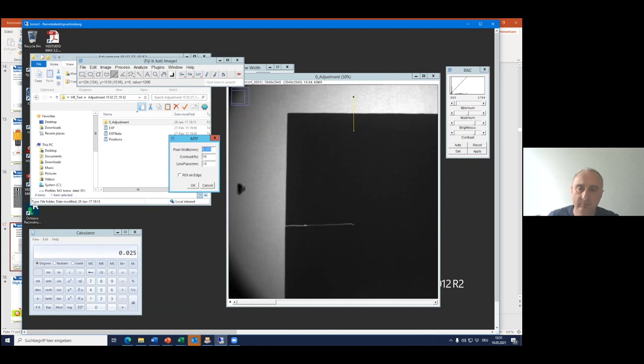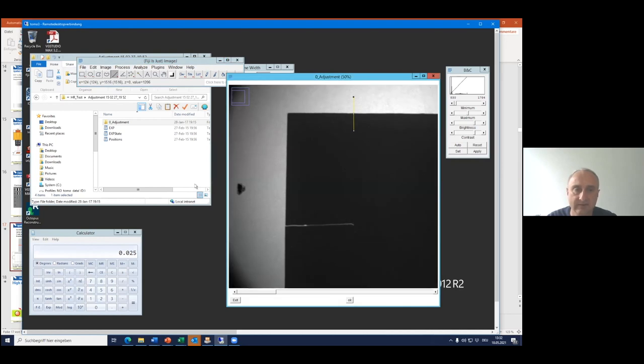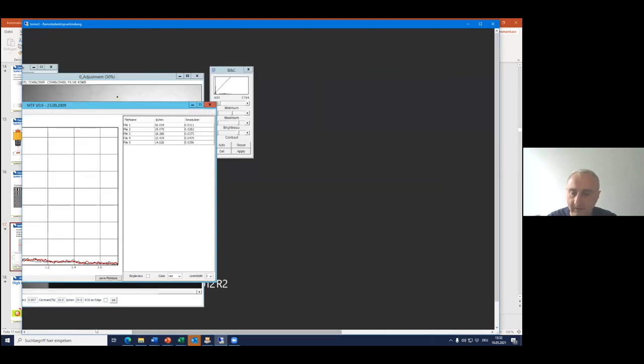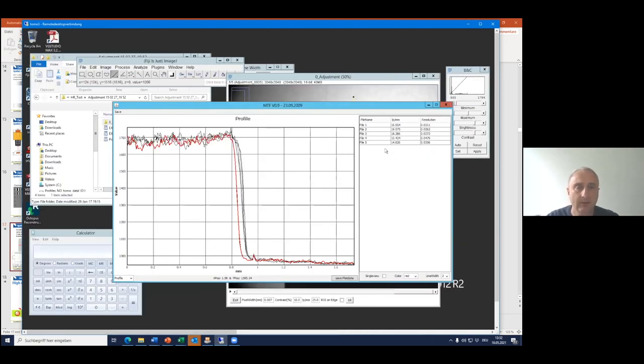It's very simple. You should just define the pixel size which we have at our detector, and it was 7 micrometer. And we want to have the contrast at 10%, and the expected line pairs per millimeter is, let's say, 25. So if you click here, then we have the response. You see, for the different pictures, we have the line pairs per millimeter and also the calculated resolution. Finally, you see that the second picture has the best resolution, and when we increase the number of the images, the resolution is decreased.